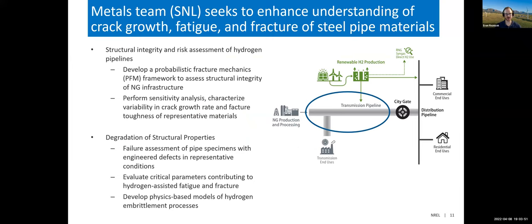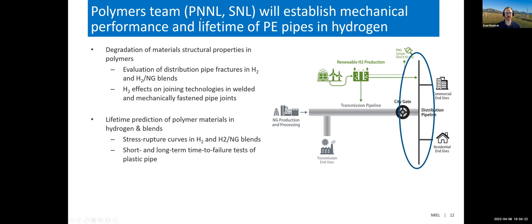So there's a need to be able to perform sensitivity analyses and characterize the variability in crack growth rates and fracture toughness of these materials in these different conditions with different defect populations. They're also focusing on degradation of structural properties, performing a lot of failure assessments to try to evaluate the critical parameters that are going to contribute to hydrogen-assisted fatigue and fracture, and develop a physics-based model that can really capture this hydrogen embrittlement process. The polymeric team at Pacific Northwest National Lab and Sandia National Lab also will be focusing on degradation and lifetime of plastic materials.